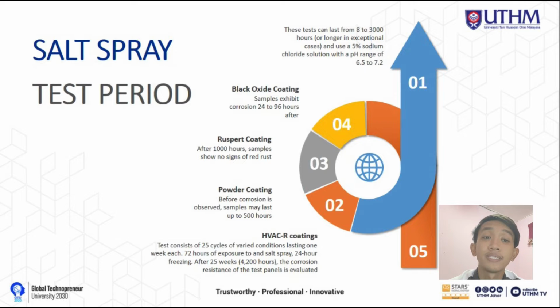Then for the HVACR coating, which is basically used in the marine industry, in the sea environment, the test basically consists of 25 cycles of varied conditions lasting 1 week each, which is 72 hours of exposure to the sun, then 72 hours of exposure to salt spray, 24 hours of freezing, and after 25 weeks, which is 4,200 hours, the corrosion resistance of the test panel is then evaluated. So that's all for the salt spray test.